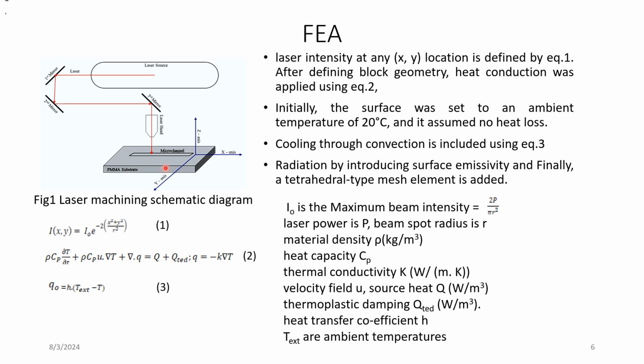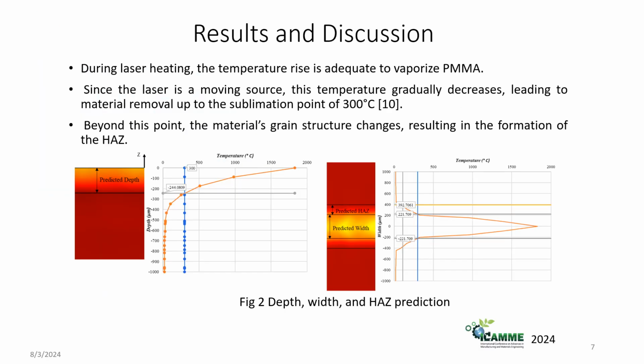In FEA, the laser intensity at any location is defined by using equation 1. After defining the block geometry, heat conduction was applied using equation 2. Initially, the surface was set to an ambient temperature of 20 degrees Celsius, and it is assumed that there is no heat loss. Cooling through convection and radiation was also introduced, and finally a tetrahedral mesh element was added and the simulation was run. Here are the results.